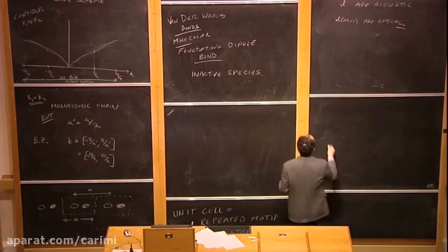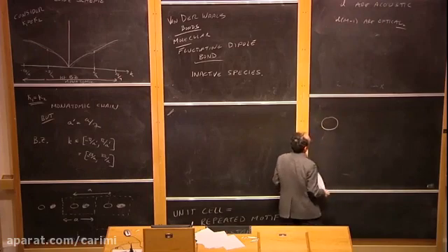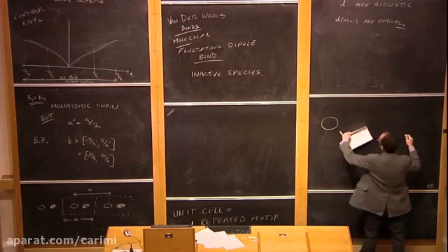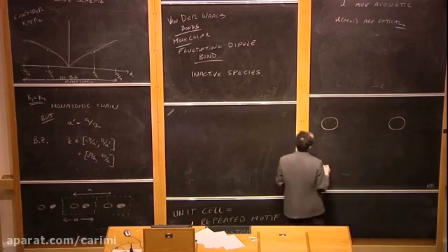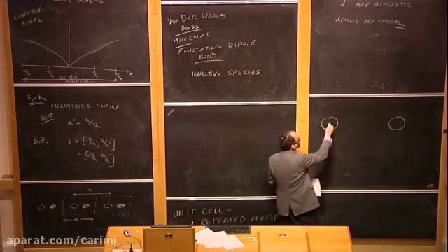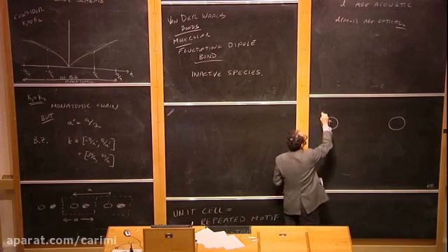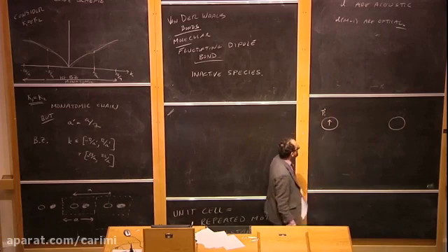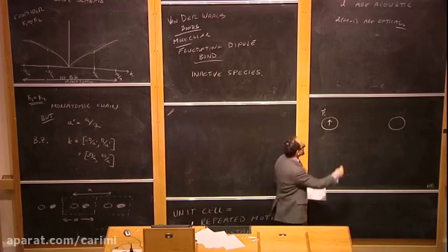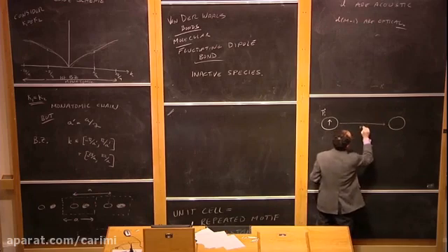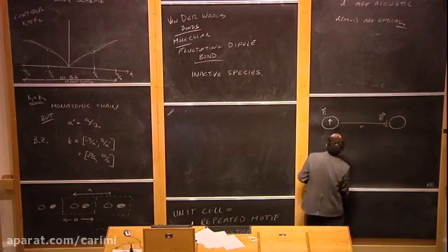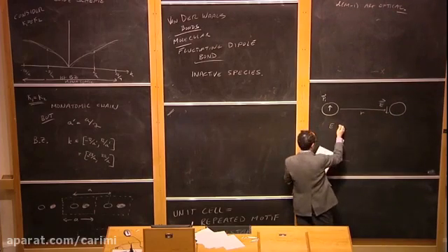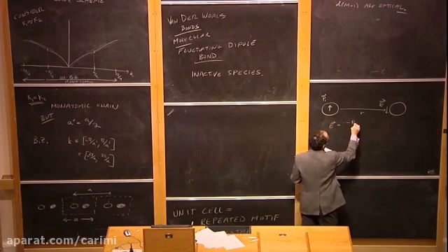The way the bond occurs is as follows. Imagine that you have, say, a nice noble gas atom over here and maybe another nice noble gas atom over here. And suppose at some moment this atom has some dipole vector P1, a polarization. Now, if you remember from your E&M, a distance r away, there will be an electric field due to that dipole moment, in this case pointing in that direction. And E will be equal to minus P1 over 4 pi epsilon naught r cubed.